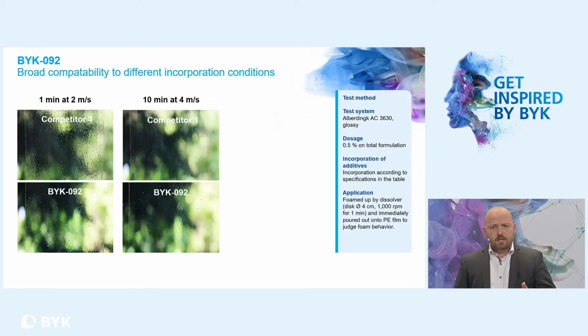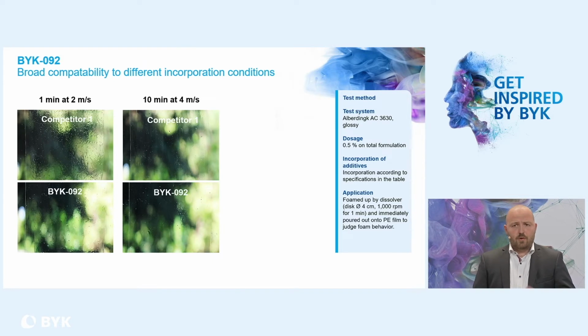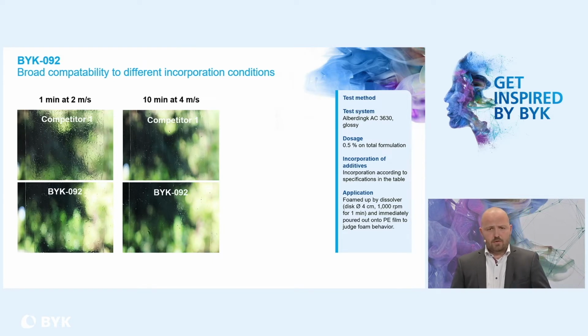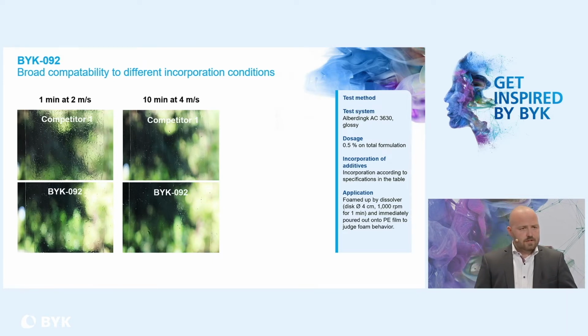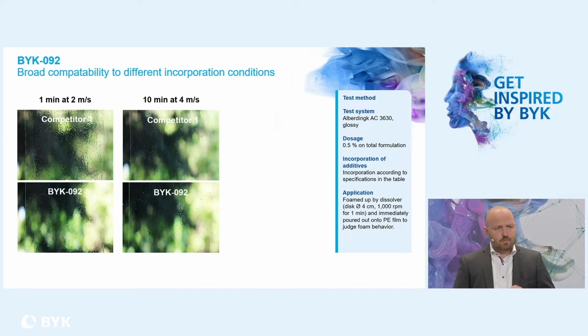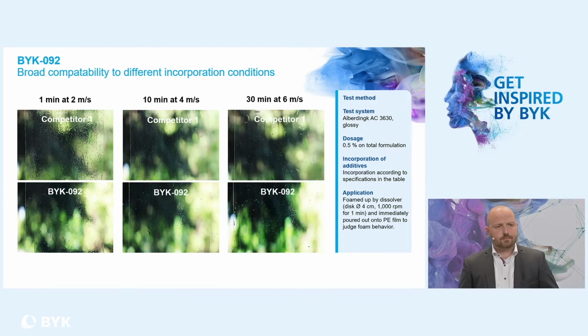When you use medium incorporation conditions, like 10 minutes at about 4 meters per second, you can see that both our market standard and the BYK 092 have a really nice surface. There's no foam, there's no cratering, but when you have a closer look, you can see that the BYK 092 has very nice transparency and no haze, while there is clearly some haze in the competitor product. So that is really nice for clear coats, and the BYK 092 is outstanding here.